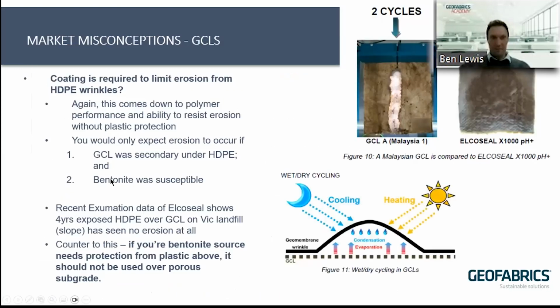This is the last one, I think. Yep. And this is just Techno. We've taken this out of our Techno, just showing you how good our GCL does perform when it comes to erosion. There's an industry standard for testing erosion. It comes up quite a lot in the industry with people concerned about GCLs eroding, and that's why a lot of people tend to like the option of putting another liner over the top of the GCL. But in reality, we're confident, and we can show it and prove it, that the bentonite will not erode over time due to the makeup of the material. So I won't go on about that too much, but I think you get the idea.